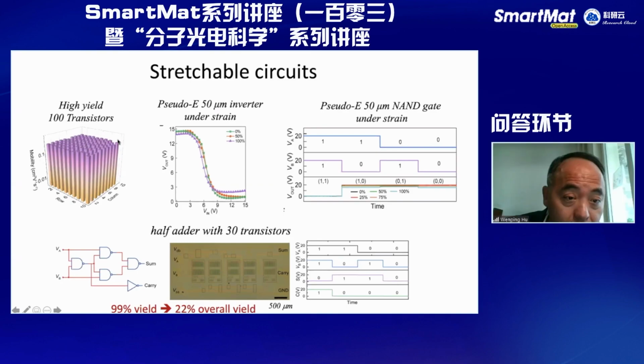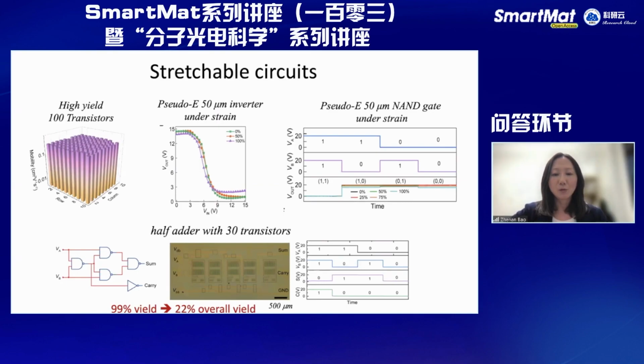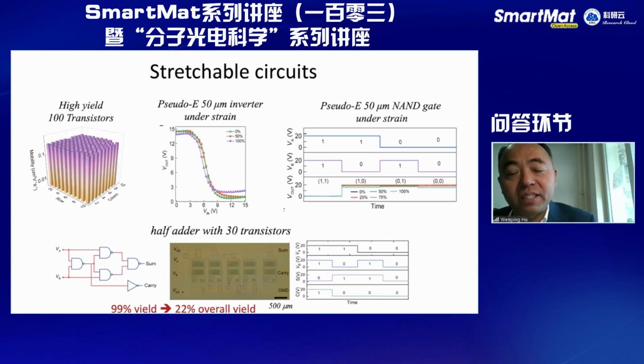Mobility is quite uniform. And with high density, the 100 transistors don't occupy a very large area. If it's low density, uniformity can sometimes be more difficult, because we have some limitations with spin coating. But I don't have the exact number. I need to check what the exact number is. But my recollection is that it's within 20%. The current output and such are quite uniform, while threshold voltage is a bit less uniform.